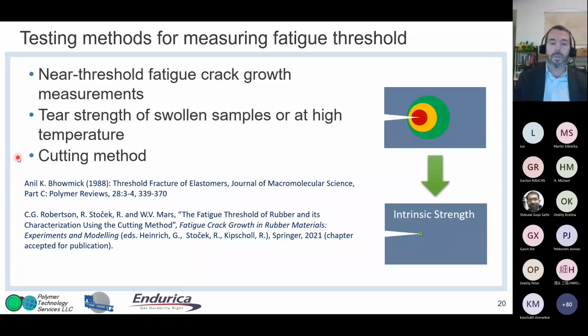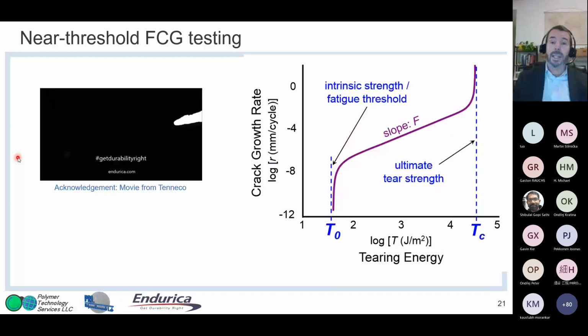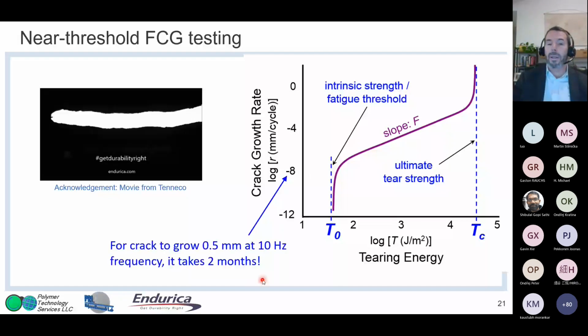So I'll go through all three of these. The first one is trying to get somewhere close to this downturn in the fatigue crack growth curve so that you can determine T0. Problem is when you do these crack growth measurements, where this turns down is somewhere around 10 to the minus eighth millimeters per cycle. And so what does that mean? Well, if you wanted to measure half a millimeter, even at 10 hertz, it would take 2 months.